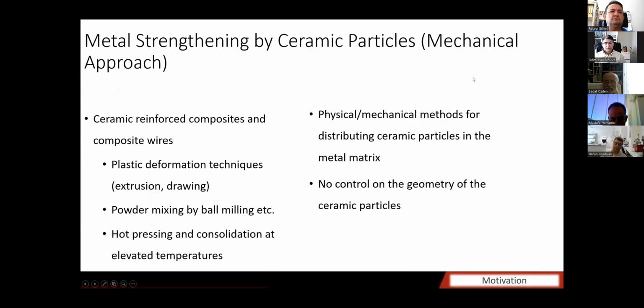So the current ceramic particle reinforced wires which are produced in industry right now use the mechanical approach. What they do is they use extrusion and drawing. Before extrusion and drawing, they mix the powder forms of ceramic particles with the metals, and they are subjected to extrusion, drawing, and other techniques. For example, powder mixing by ball milling and other techniques are also used. And then they are hot pressed. A series of treatments which I have shown you in the previous slides, and then eventually the ceramic particle reinforced composites are produced. The ceramic particles work as a strengthening element of the composites. This is a mechanical approach.